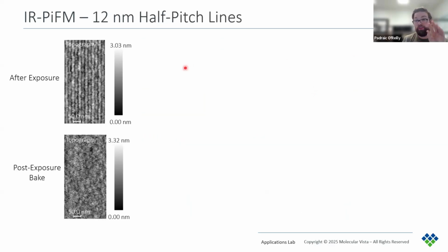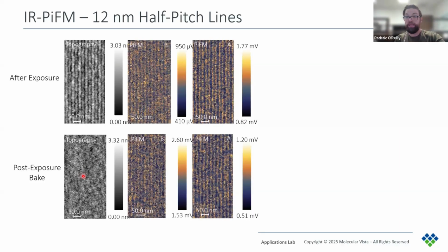So here we have the topography images for the exposure and post-exposure bake samples. The first thing you might notice here is that these features, these lines, essentially disappear after the bake. So AFM alone will not tell you much about the post-exposure bake sample. However, we can still see the chemical contrast in PiFM, even for these 12 nanometer half pitch lines.